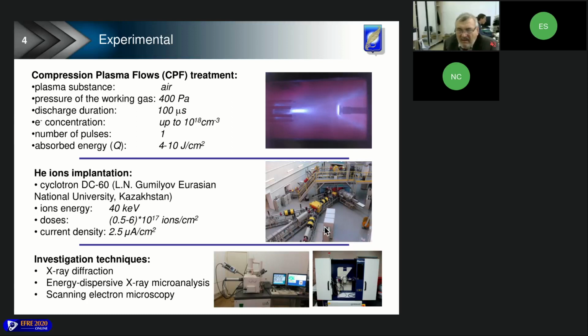In general, the heat flux absorbed by the surface layer, I mean the heat flux registered by the calorimeter, can reach up to 60 or 70 joules per square centimeter per pulse. In this experiment, the energy absorbed by the surface layer of the target was varied in the range of 4 to 10 joules per square centimeter by changing the distance between the sample and the cathode.